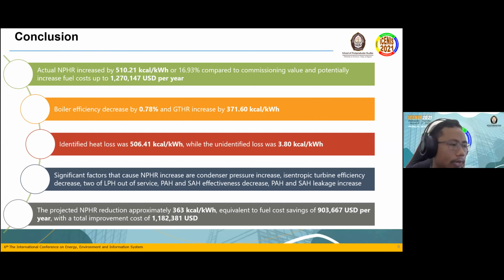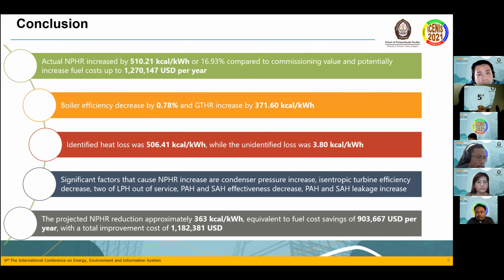The conclusion of our research is that the actual heat rate increased by 510 kilocalorie per kilowatt hour, or 16.9%, compared to the commissioning value. This increment is due to boiler efficiency decreasing by 0.78% and gross turbine heat rate increasing by 371 kilocalorie per kilowatt hour. Identified heat loss was 506 kilocalorie per kilowatt hour, while the unidentified losses are 3.8 kilocalorie per kilowatt hour.